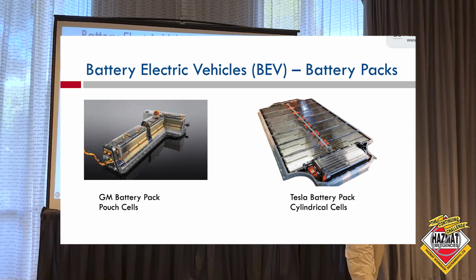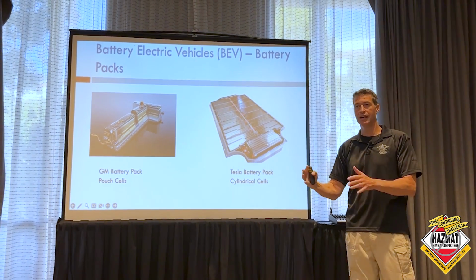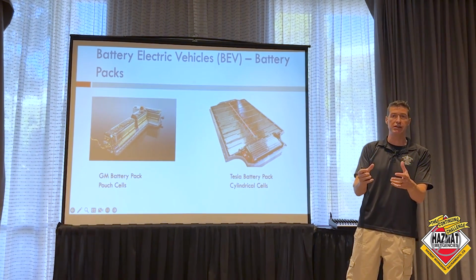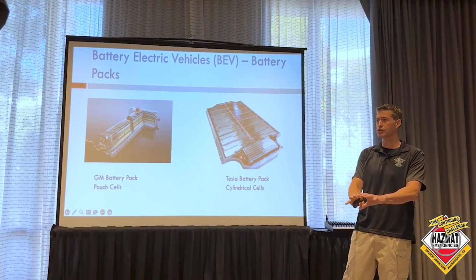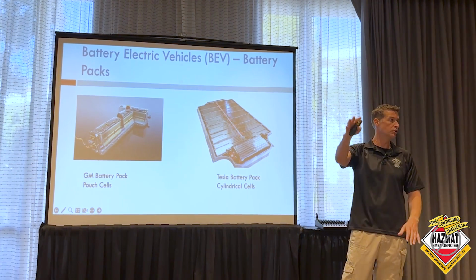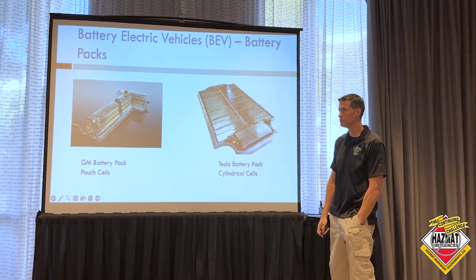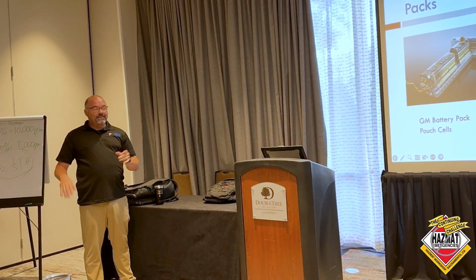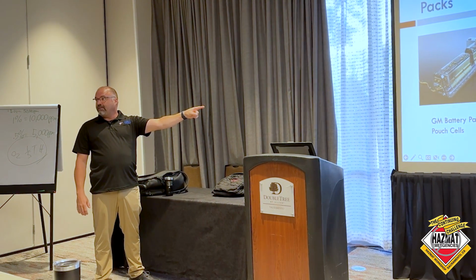And they're by design separated to prevent the propagation of a thermal runaway. So the intent, and they're getting better and better, is that if you have one module that fails, that's the only thing that fails in the car. It does its thing and it's done, and they can just replace that module and put a new one on and you're good to go. They're not there yet, but that's the intent. Just to keep in perspective, that cell phone charger you have has one cell, scooters have like 50 to 80 cells, and a Tesla has about 7,000 cells. All the same, just packed differently.